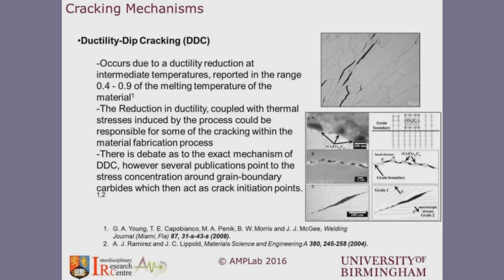The mechanism itself is not fairly clear about why it happens, but there's a chance that it's accompanied with the presence of phases like carbides causing incoherency on the grain boundaries, combined with the residual stresses, resulting in the formation of cracks.